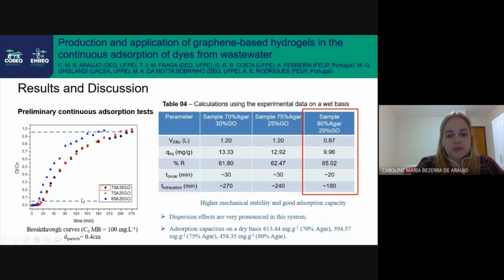But in all cases, dispersion effects were very pronounced, as the hydrogel is composed of around 98% of water. We also have these results on a dry basis, and for the 3 samples here, the adsorption capacities were over 450 milligrams per gram.